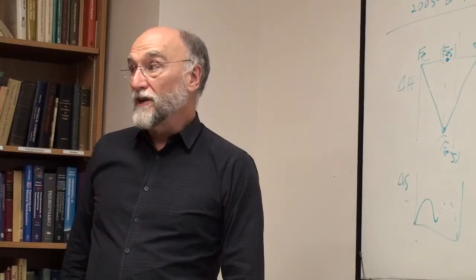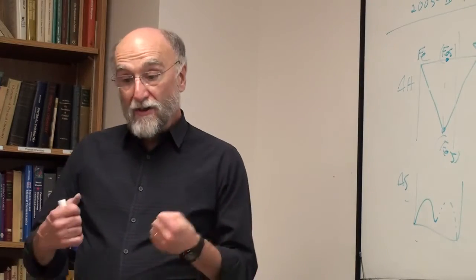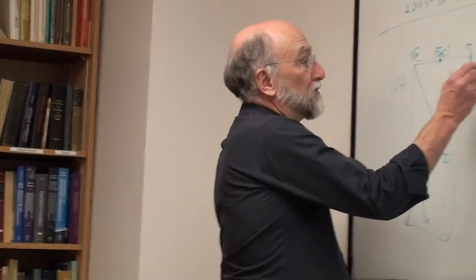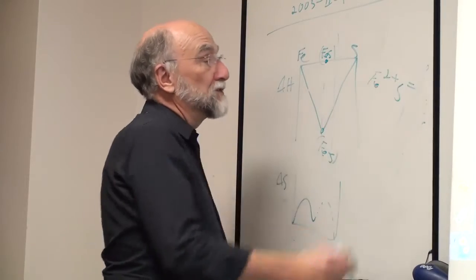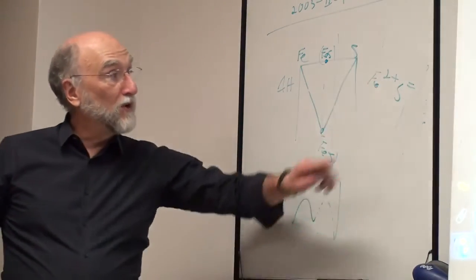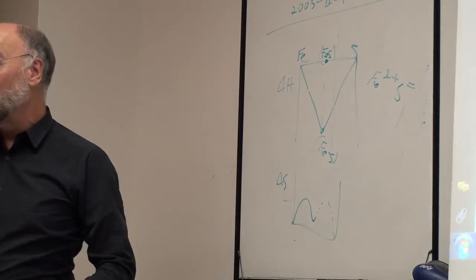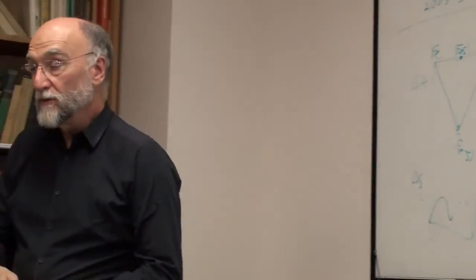And although liquid FeS does, there are enough delocalized electrons that it still remains an electronic conductor. It's not pure. You could treat it as Fe2+ S2-, but not all the electrons tend to be localized. There tend to be some that are loose and are forming an electron cloud which can conduct electricity.